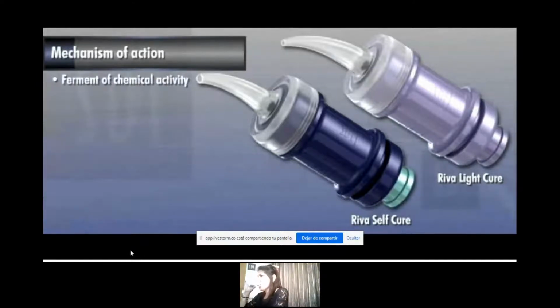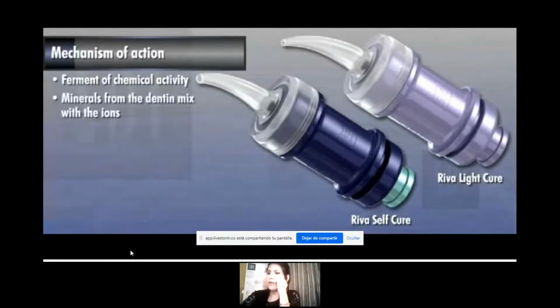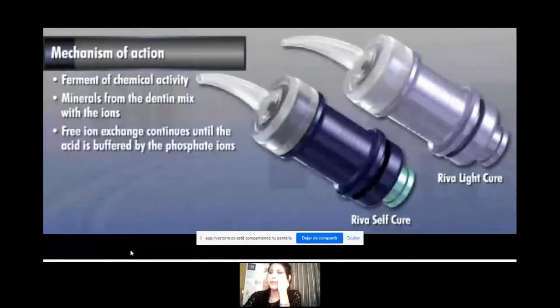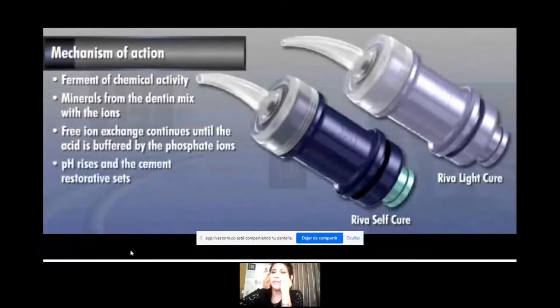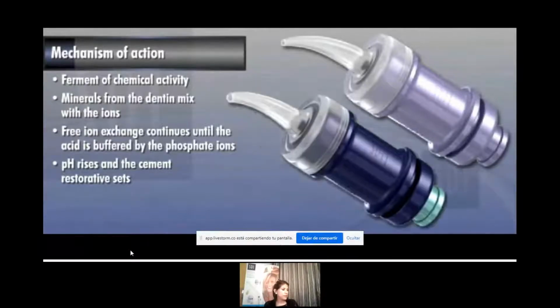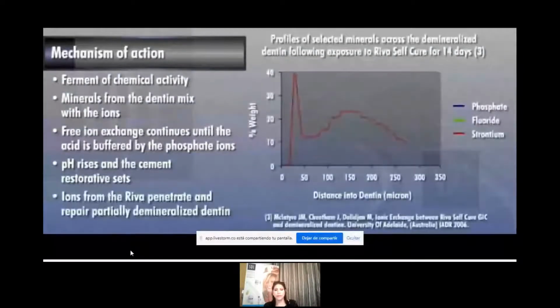Immediately following the placement of the glass ionomer, a ferment of chemical activity takes place under the restorative. Available minerals from the dentin mix with the ions released from Riva, creating a free ion exchange that continues until the acid is buffered by the phosphate ions. As the pH rises, the cement restorative sets and the ion exchange slows down. It has been shown that strontium, fluoride, and phosphate ions from the Riva can penetrate a considerable distance into partially demineralized dentin, aiding in its repair.